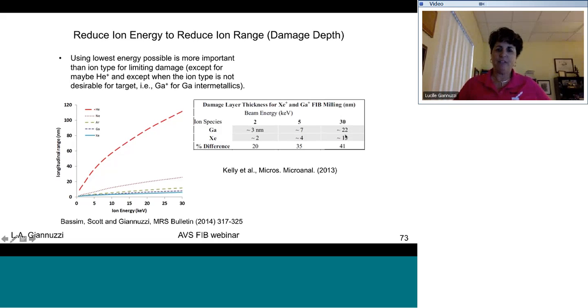As we go to 5 kV, the difference is less, and as we go to 2 kV, the difference is even less. And this is shown here by this graph, right? So as we go to lower and lower energy, the difference between ions becomes less, or becomes insignificant. And so my story would be, it doesn't really matter what ion you use per se, as long as you can get this ion energy down really, really low. Now, you might want a particular ion over another because it may react with your sample, but that's another story. Okay?